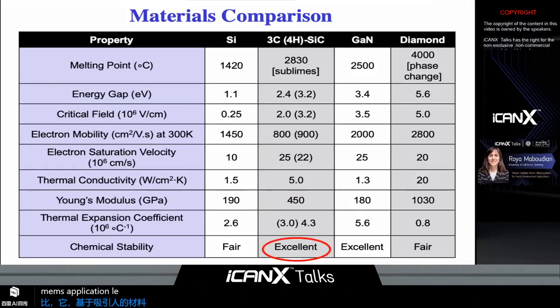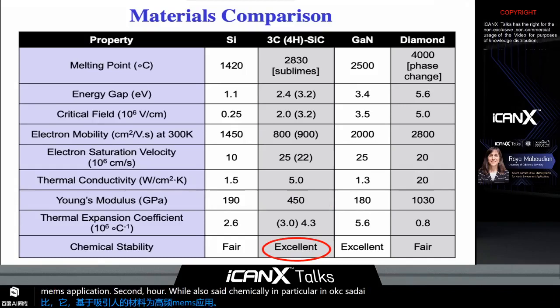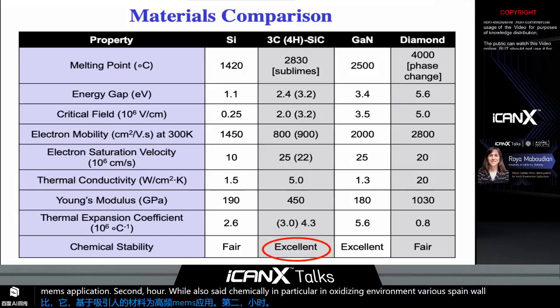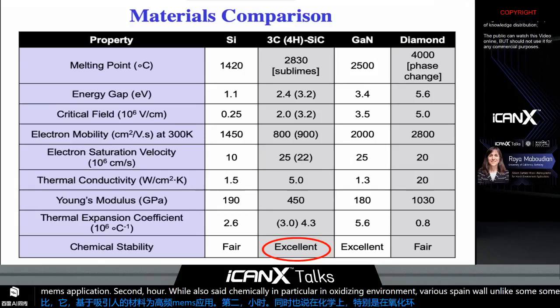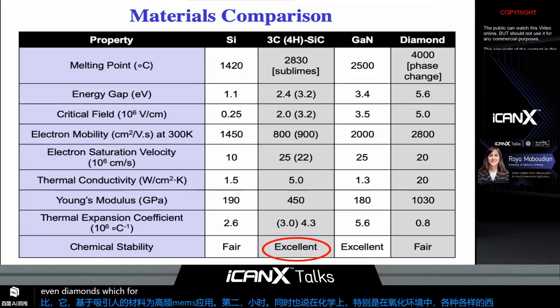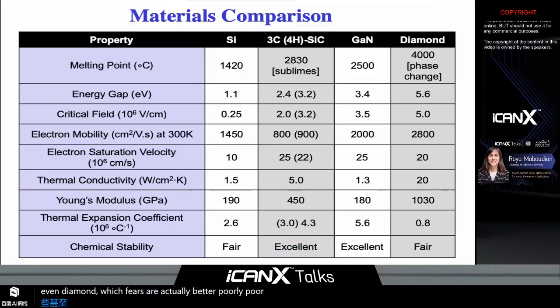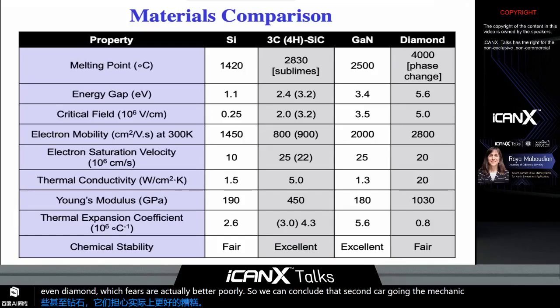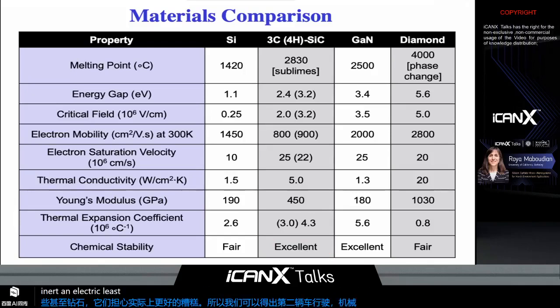Silicon carbide also is chemically, in particular in oxidizing environment, very stable, unlike silicon and even diamond, which fares actually rather poorly. So we can conclude that silicon carbide is a mechanically robust, chemically inert, and electrically stable wide bandgap semiconductor material.